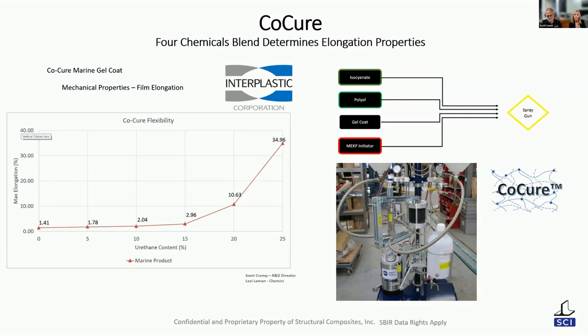And for coatings, same thing. We don't want our coatings cracking ahead of our laminate. And so our secret decoder ring is really simple here. This is the percent of urethane mixed into, in this case, a coating. So it's gel coat with its catalyst and then various amounts of urethane.